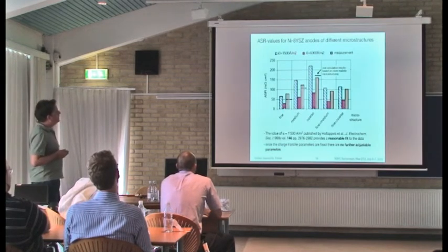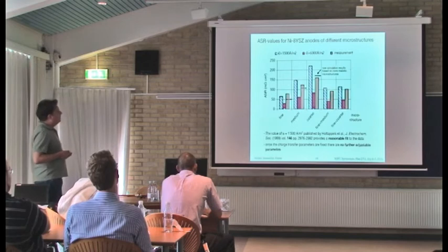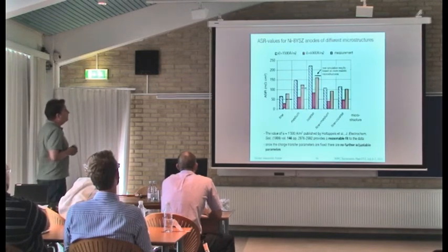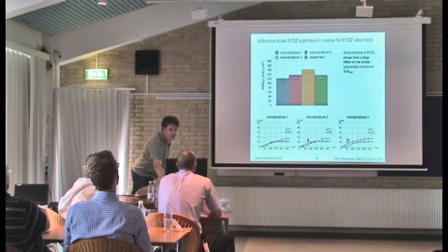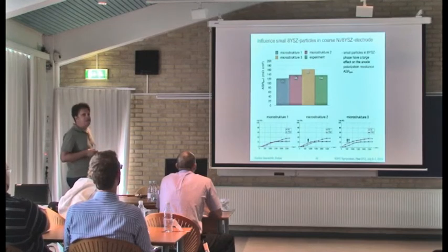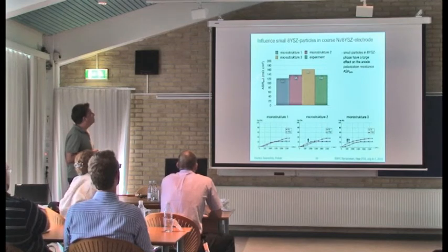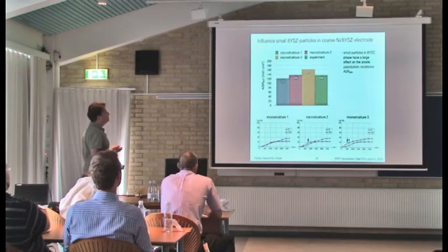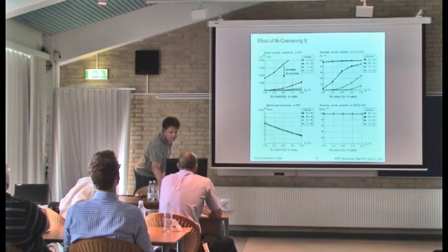But of course you have the exchange current density as a kind of free parameter. Those are the latest results I got, where I used the microstructure continuous particle size distributions as obtained by Lorentz, and you see for those 3 cases here, going from a fine to a coarse electrode, they agree surprisingly well with the experimental data. Another issue is, what do small quantities of small particles do? You see here the polarization resistance of an electrode, and how again small changes in the microstructure make quite a big shift in the resistance value. But overall, the values are pretty close to the experimental results anyway.